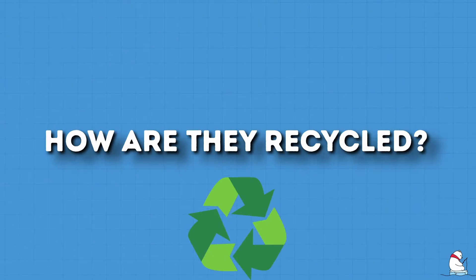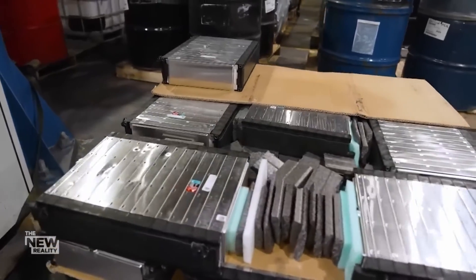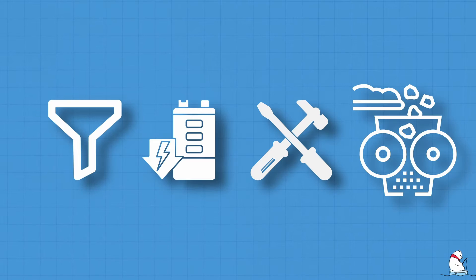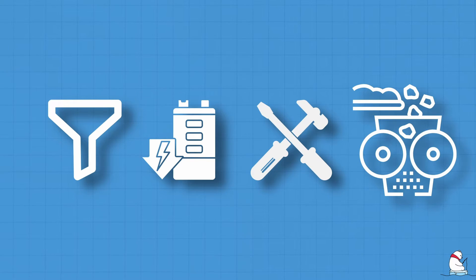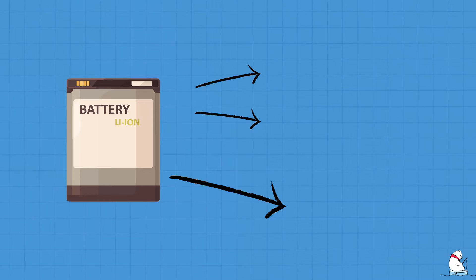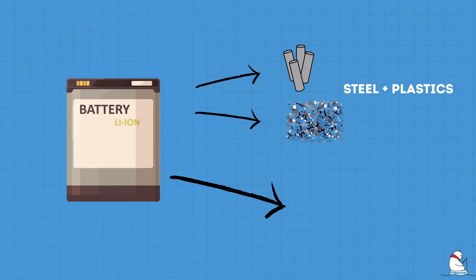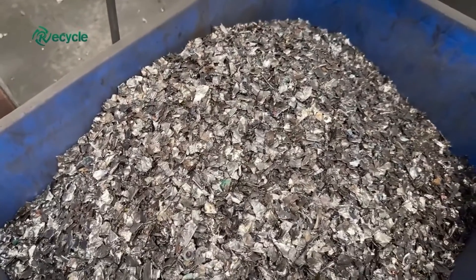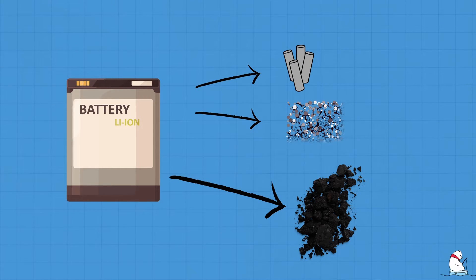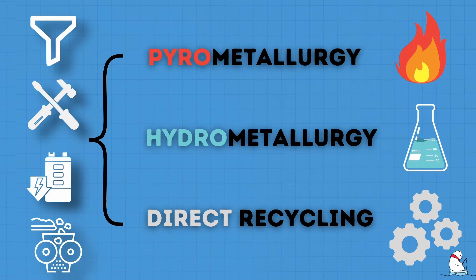So how are lithium batteries recycled? Well, first they need to be collected. Once collected and sent to be recycled, there are three main processes: pyrometallurgy, hydrometallurgy, and direct recycling. Generally, all three processes first go through some sorting, discharging, dismantling, and crushing. In these steps, you separate plastics and steel from the rest and can recover these materials. The important end product you get — containing all the metals such as lithium — is called black mass. The next stage is where the processes mainly differ.